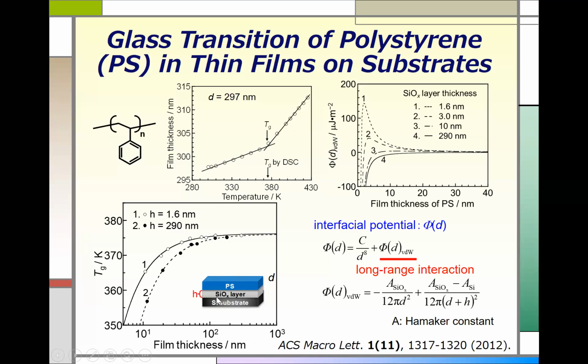Then look at this figure. This is the thickness dependence of the glass transition temperature, right? And you see that with decreasing thickness, Tg goes down like this. And why is that? See here, this is the geometry of the sample. As I told you, at the surface, molecular motion, I mean chain movement, is pretty much enhanced in comparison with that in the internal region of the film. Why is that? It's because polymer chains are not surrounded by other chains at the surface, right? So with decreasing thickness, the ratio of surface area to the total volume is going to be extremely increased. That is why we see this kind of behavior.